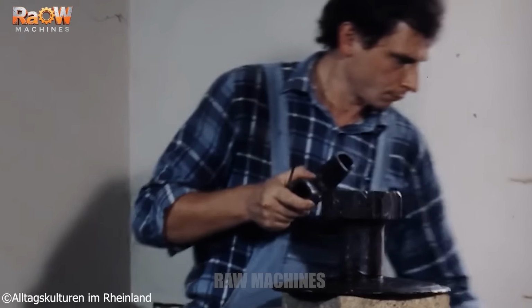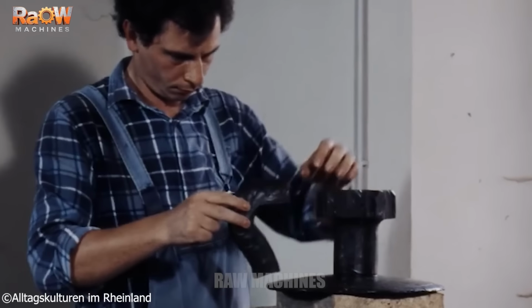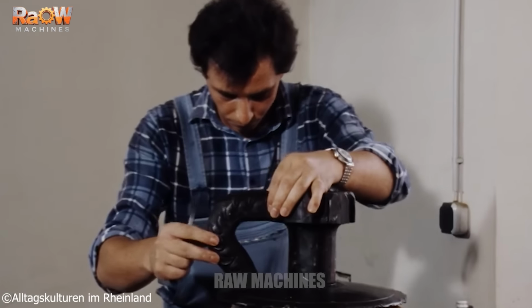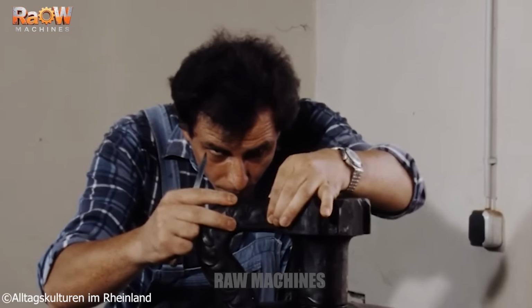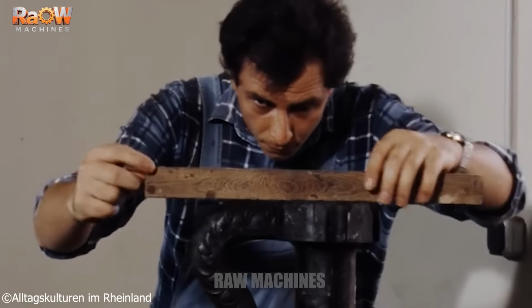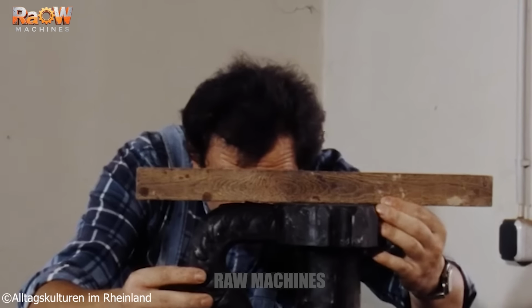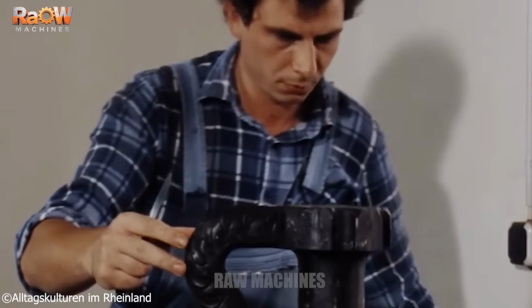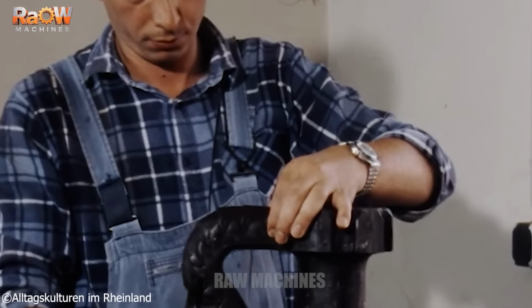The bell crown consists of a central hub and 6 cannons. After the plaster molds are removed, the wax components are precisely assembled on a turntable and subsequently coated with successive layers of fine clay. The number of layers is recorded using reference marks to control the mold thickness.